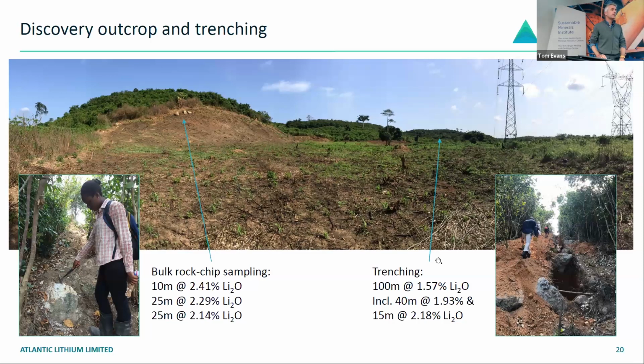It's highly weathered, and sampling of lithium pegmatites at that time was a bit of a struggle. Labs hadn't really got it down packed in terms of their calibrations. So we had lab issues. We didn't really know what we were sampling. We could see there were white felsic rocks, but we didn't know what spodumene looked like, especially when it's weathered. And then also the samples we initially collected were weathered, and they all came back at around 0.1, 0.2, not the 1 or 2% we were expecting from those geological survey reports.